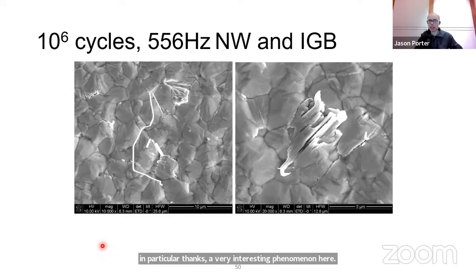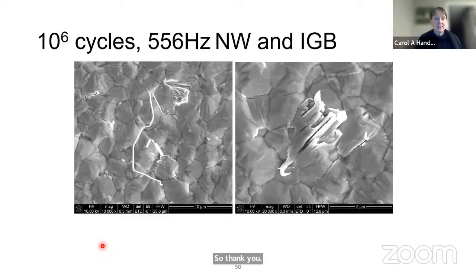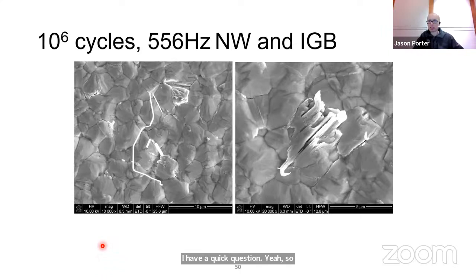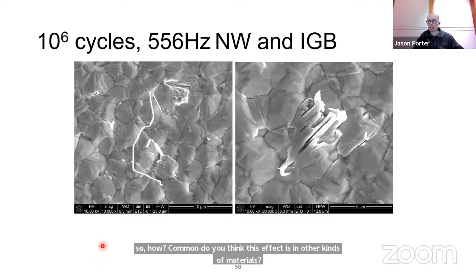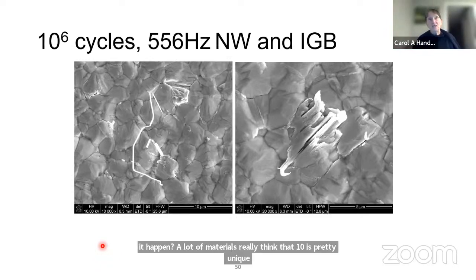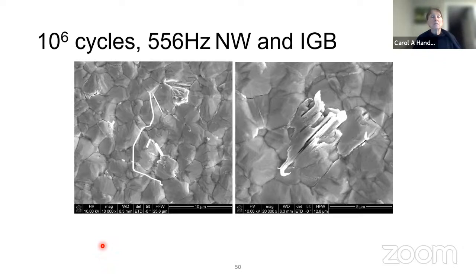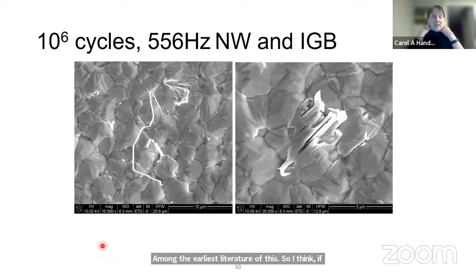I have a quick question. Please. So how common do you think this effect is in other kinds of materials? Does it happen in a lot of materials, or do you think that tin is pretty unique? So first of all, tin is not unique. Another system that does this is aluminum. And aluminum has a natural oxide layer on it, and it's been known to happen for many years in aluminum films. That is among the earliest literature in this. So I think if you can make the capping layer thick enough, you can end up suppressing it, but it also depends upon what stresses you impart to it.